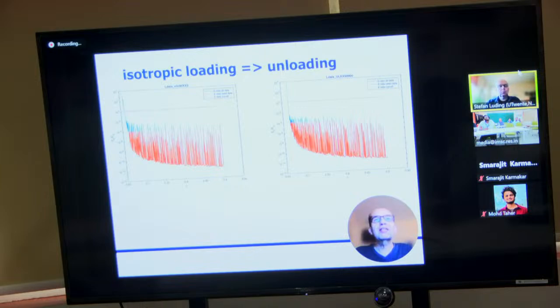When we plot kinetic energy for those two cases, we see something similar to what we saw under shear. There's an elastic baseline, the lower envelope of the data. There are peaks, events, which are happening under isotropic compression. So what I showed you before for shear also happens for isotropic compression, for loading and unloading with different probabilities, but that's something for further analysis.